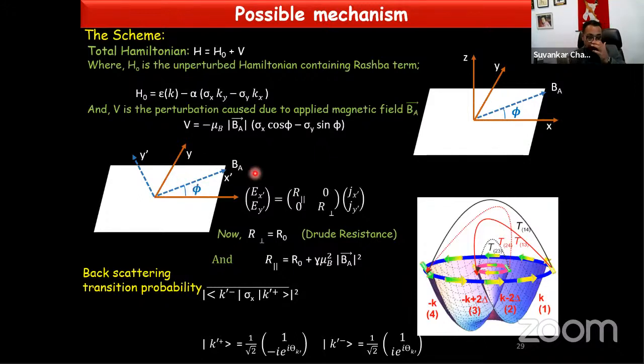Okay, so you can calculate this resistivity in the frame of reference of this rotating frame. What you basically calculate is the transition probability by using the Fermi golden rule. And you can calculate the resistance which is perpendicular to the applied magnetic field, which gives you nothing but the Drude resistance. So the important component is the R parallel to the B.